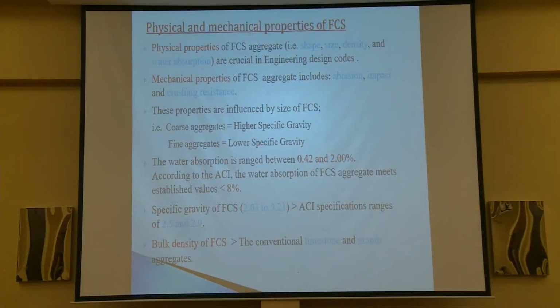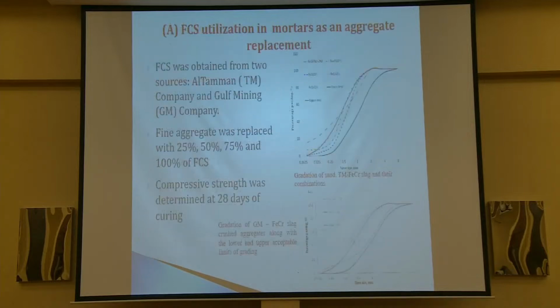And therefore, we find that the water absorption ranges between 0.42 and 2%, which is almost comparable to aggregates, and the specific gravity is also similar to aggregates, ranging from 2.63 to 3.21. And therefore, we studied two types of ferrochrome slag, from two different factories. And this is the grading. You also need to know the grading. The grading is very important, because poorly graded material will affect the concrete properties.